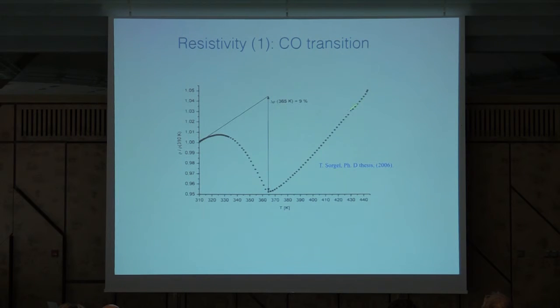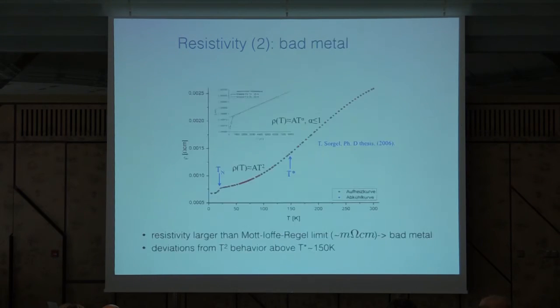So you go down, and according to the definition we saw this morning, this is a metal. It goes up with temperature. At lower temperature, it's also a metal, but you have this jump here by about 10%. Now, what is probably more interesting is the low-temperature region. Forget about this magnetic ordering that occurs at very low temperatures. All this part here, you have a quadratic temperature dependence, then a crossover to something that looks linear and then bends down. The values here are in the milliohm centimeter range, which, if you remember from this morning, is a bad metal.